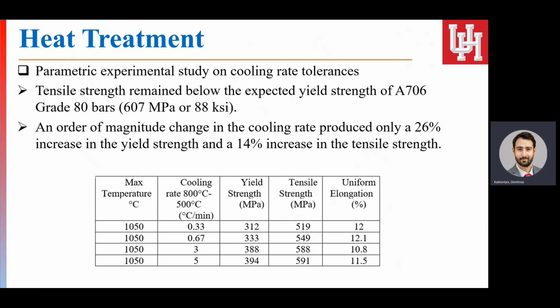So what we did is that we varied the cooling rate from 0.33 to 5, which is a significant variation. And what we noticed is that, in fact, the tensile strength in all cases remained below the expected yield strength of A706 grade 80 bars, which is the bar type on which we performed this heat treatment. So you see that in all cases, the tensile strength remained below this target limit.